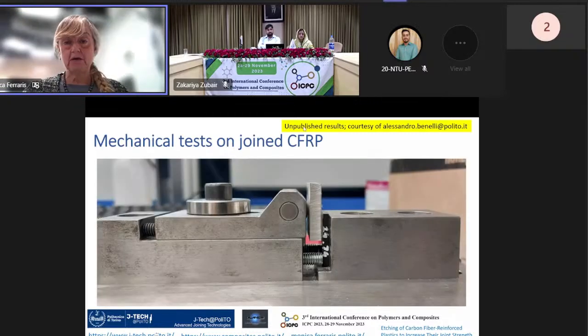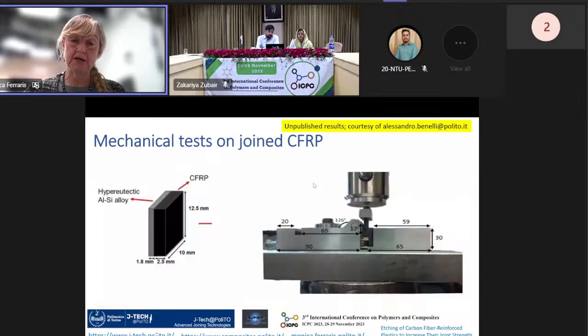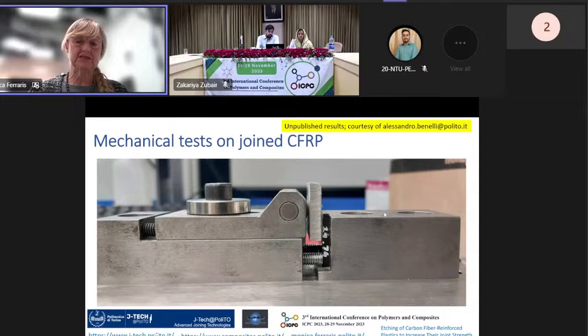You can see there our setup: you have aluminum here and CFRP here, and then we push on aluminum, or as I showed you before, two pieces of CFRP here. Again, this is not pure shear. We are perfectly aware that there are some stress concentrations here and there, but it is at least one simple way to test the behavior of many different etchings.